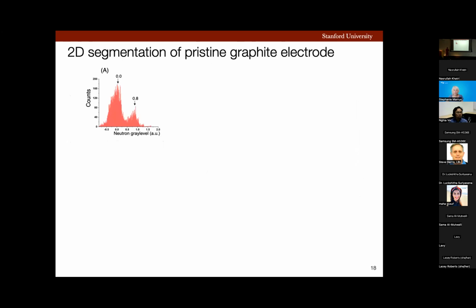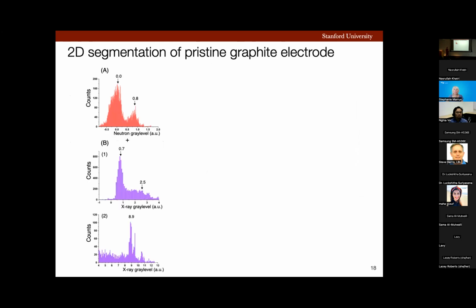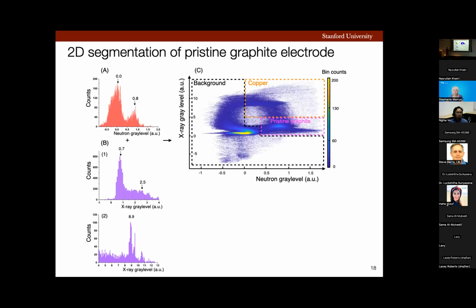So my neutron image gave me this neutron histogram, which shows two peaks. My X-ray image of the pristine graphite gave me my X-ray histogram. Now the x-axis of this X-ray histogram is longer, as you would see here, as compared to that of the neutron histogram. Therefore, these peaks appear stretched. Then I combined this data to create this two-dimensional histogram. Here on the x-axis, we have neutron gray level values. On the y-axis, we have X-ray gray level values.